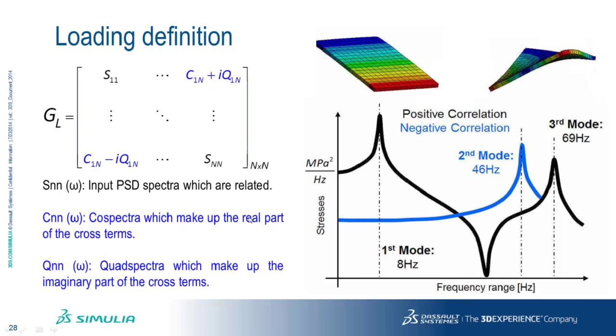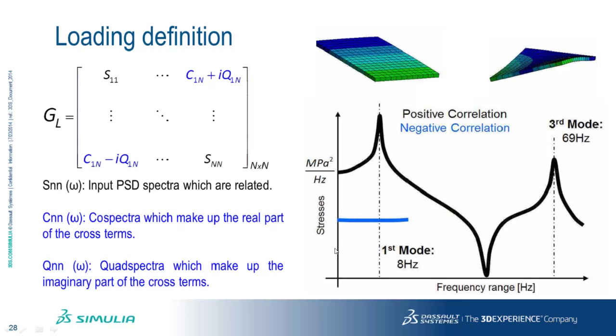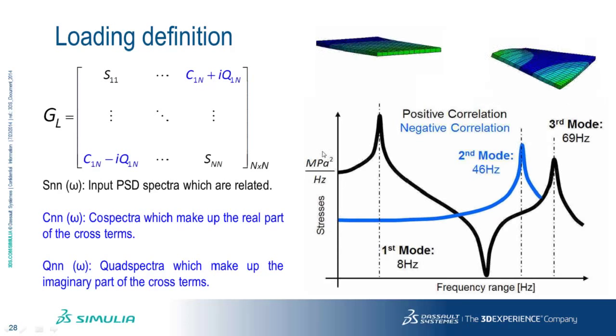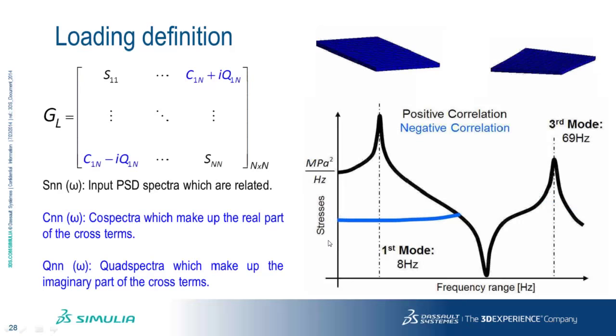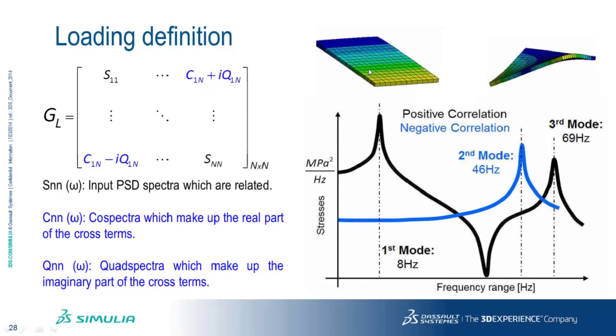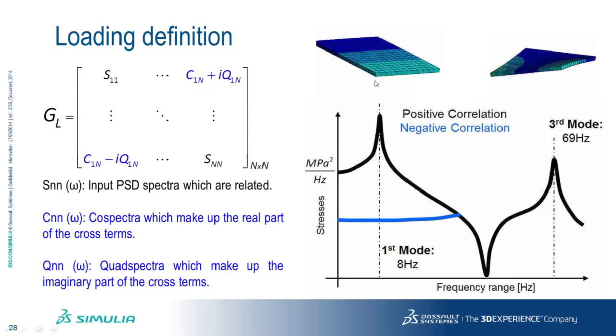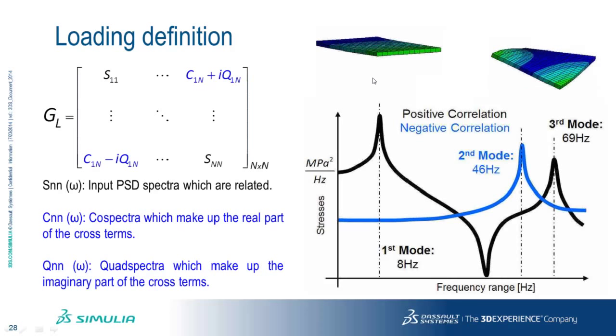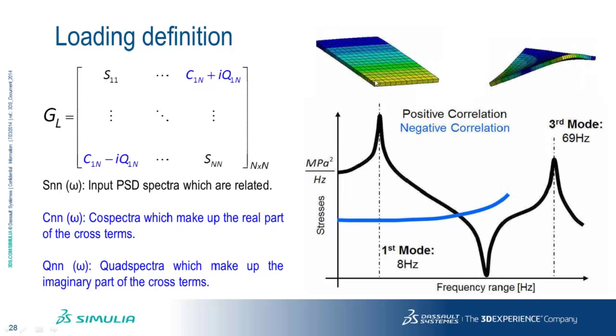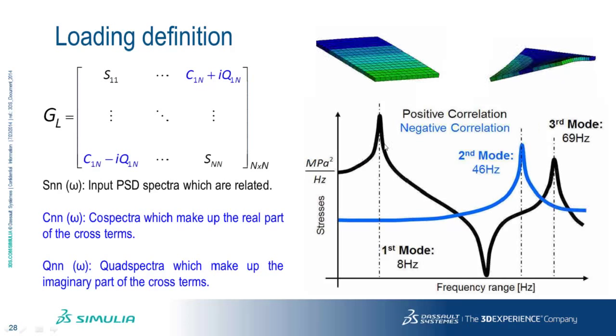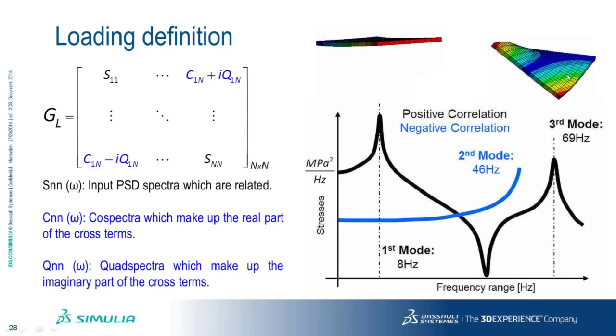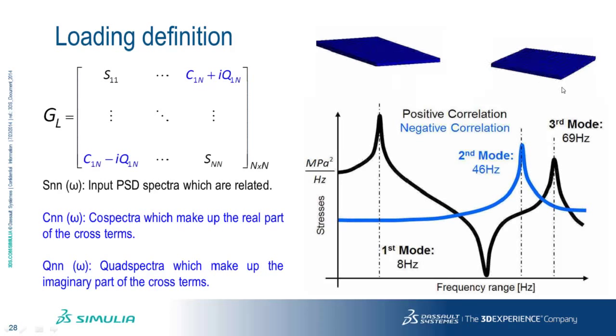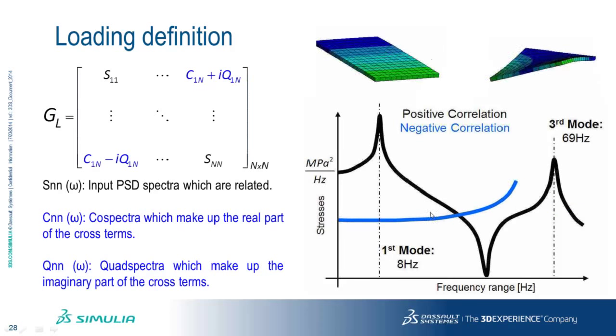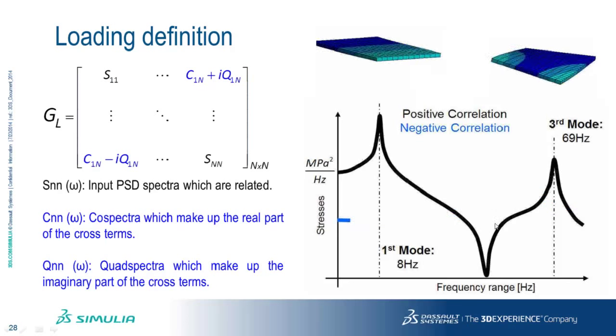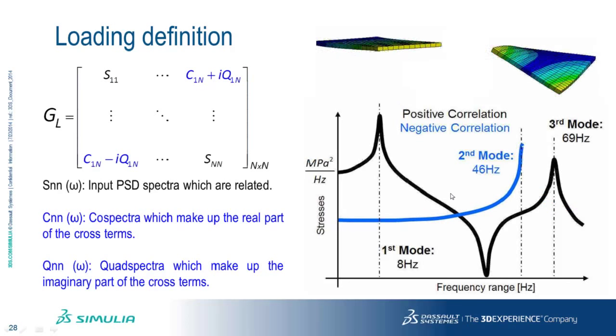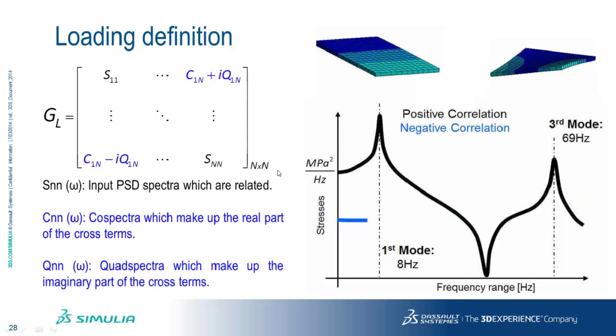To show you how important the phase is, what we have here is the PSD of the stresses at one point on our model. If we ignore phase and assume that the two loads on this little strip are cycling in phase, then we get the black response, two mode shapes. If we're assuming that they are cycling out of phase, as we've shown on the right-hand side, then we get quite a different response. So that's the importance of including phase information in our loading, if we can retain it.